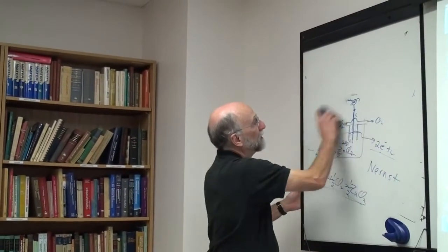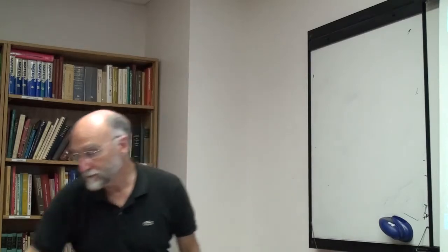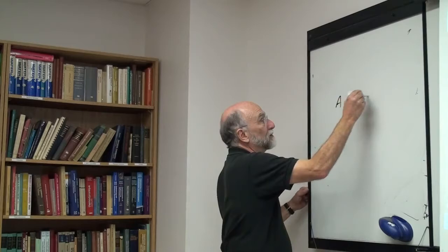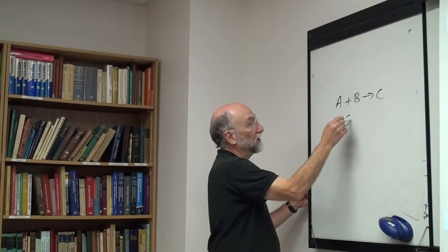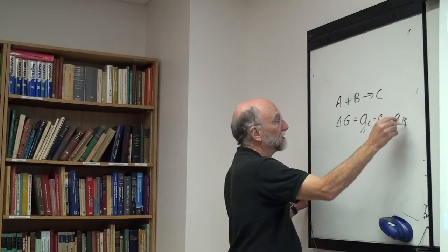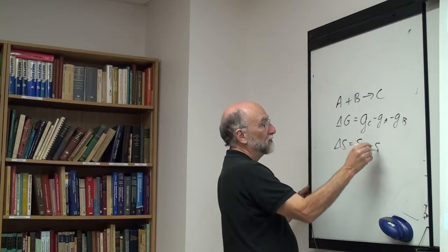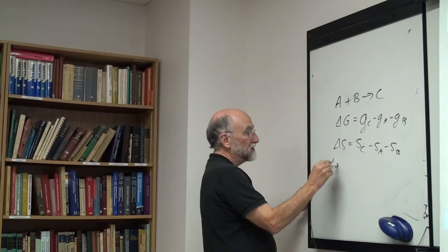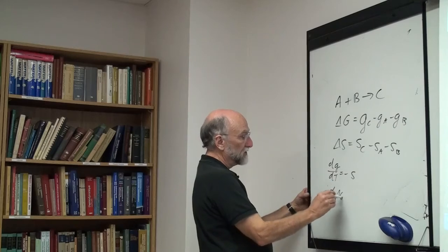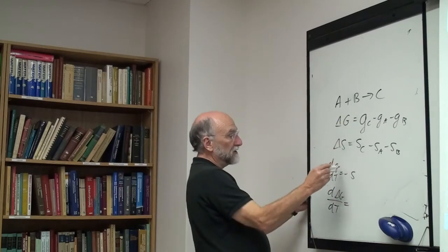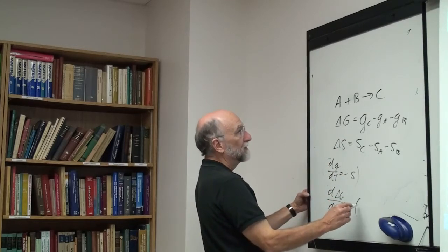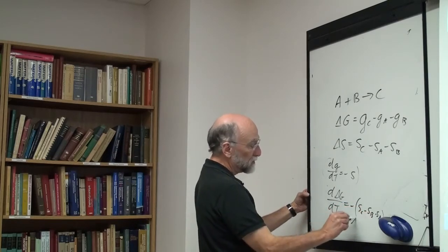You can also rearrange this equation a little bit, and you end up with an equivalent expression that d(G/T) over d(1/T) at constant P is equal to H. Now these equations apply to both the initial and final states of a process. Let's say the first equation, number 52, applies to a specific compound. But let us say I have a system A plus B produces C as my chemical reaction. For this reaction, delta G is G of C minus G of A minus G of B. Delta S is equal to S of C minus S of A minus S of B. But dG/dT is minus S, so d delta G/dT would be minus S_C minus S_B minus S_A, or in other words, minus delta S.